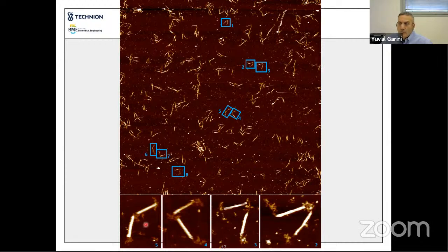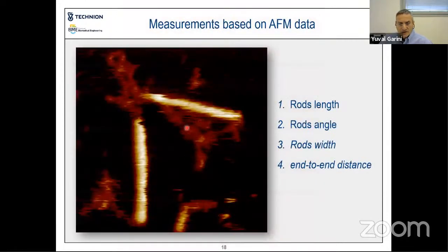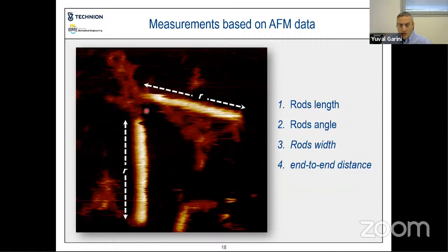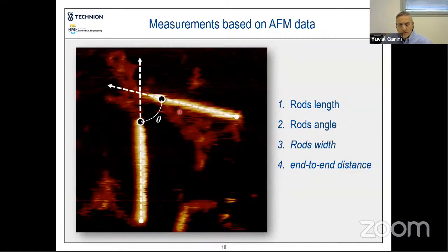And then there is no way to confuse the single-stranded DNA of any two structures. And we have many structures to select from. So once we have those structures, we can really perform a measurement. So you can see the structure. And just for verifying that the structure is correct, we measured the length of the rods, which is supposed to be 100 nanometer. We measured the angle just in order to make sure that there is no specific angle.